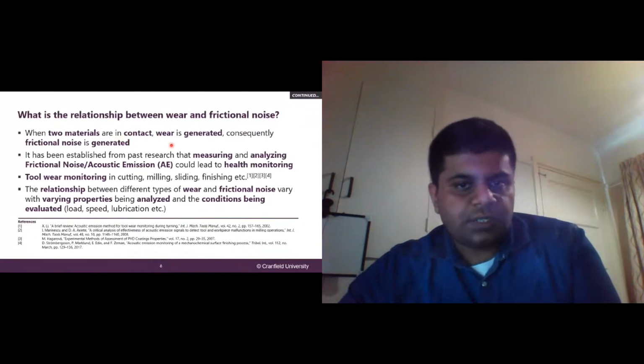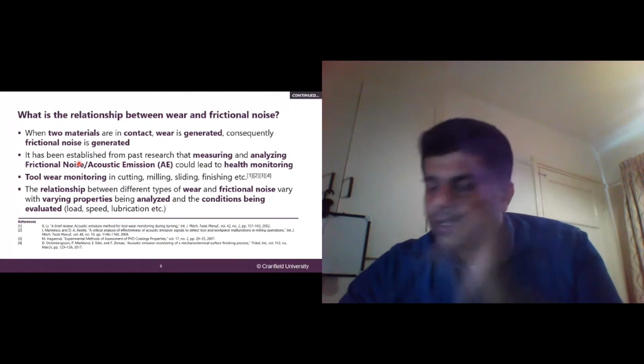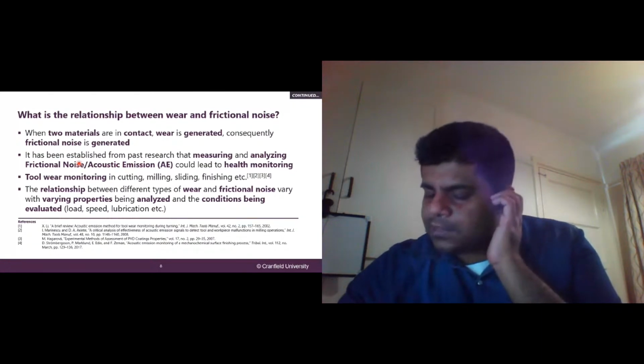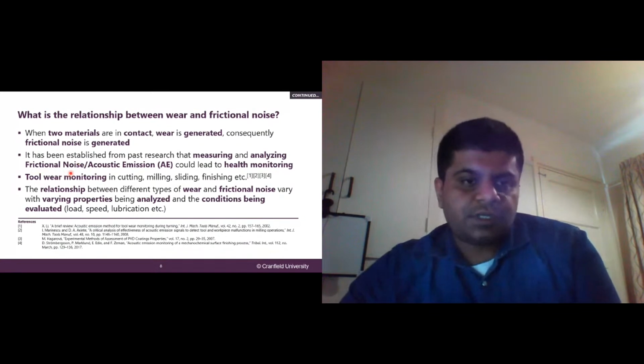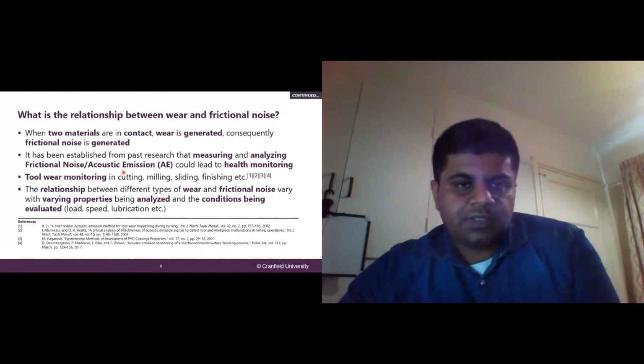So when two materials are in contact, wear is generated. Consequently, frictional noise is also generated. We can compare the two as the same, the acoustic emission and frictional noise. Some may actually have an argument against this, but once you change the frictional noise signal into an FFT, you get the same as the acoustic emission signal. So they are very much comparable as seen in the literature.